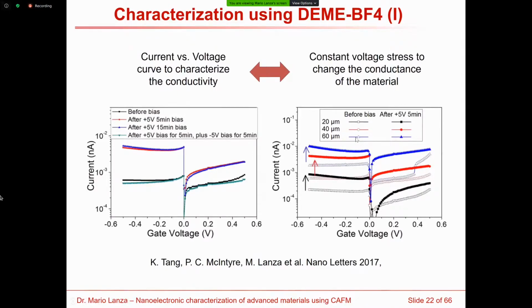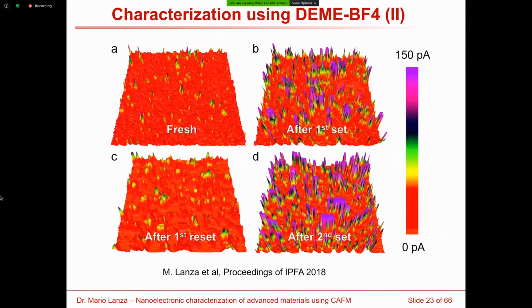And by doing tests in different areas, we observe that both the high resistive state and the low resistive state in this stress are dependent on the area, which makes us think that this is a distributed effect. But because we are applying the test with the probe station, we cannot be sure about this. So the way that we have to confirm this is by doing electrical maps. These electrical maps were done by one of my students in the fresh samples, after the first set, after the first reset, and after the second set. And you can clearly see that the density of spots increases and decreases, confirming that first, there is resistive switching, and second, this is a distributed effect.